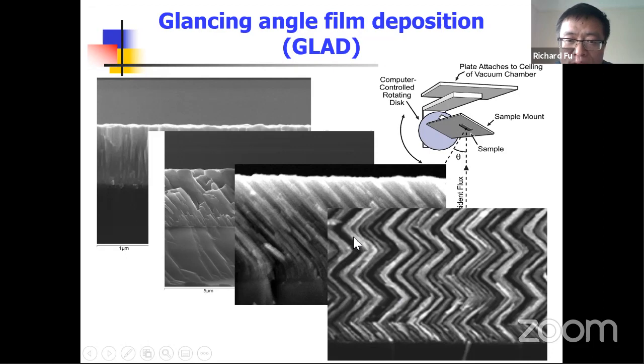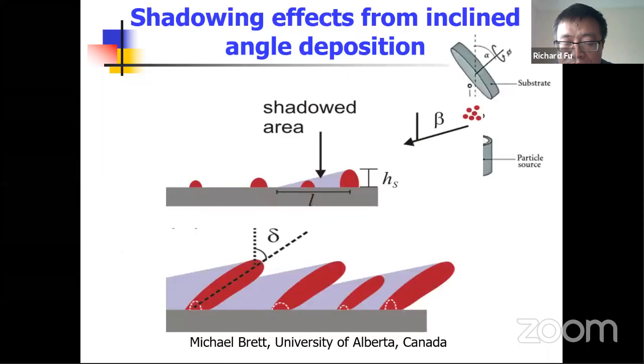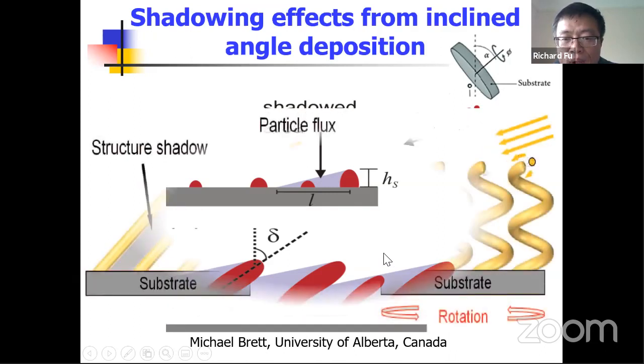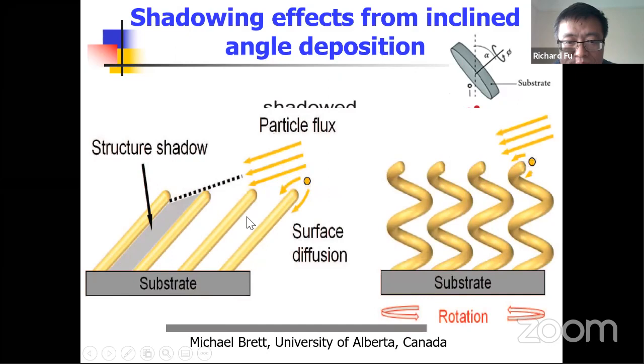So we grow this film for piezoelectric and surface acoustic wave applications to generate shear waves. If you tilt significantly, for example above 50, 60 degrees, then a nanostructure will be formed because of the shadow effect. There will be a shadow behind it, so you couldn't deposit any film. That means you can deposit a film which is porous and nanostructured.